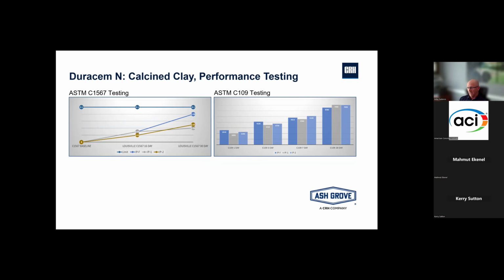As you can see on the graph here on the left, the dark blue line is the threshold, 0.1 for the testing. Our Duracem F at 30 days was around 0.08, so it was getting the job done successfully. But the calcined clay, as you can see from the brown and the gray lines on the graph here, did an even better job. It basically cut that in half. So it improved the performance and made everybody comfortable, when you're doing a road project as a Department of Transportation, that this is going to do its job as said. No matter the conditions, it's going to handle the ASR there.